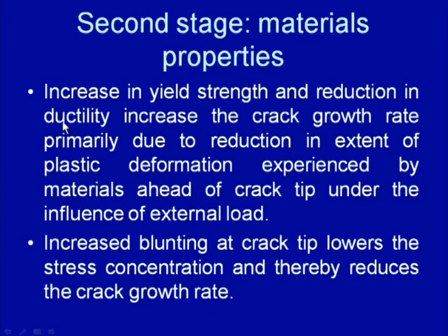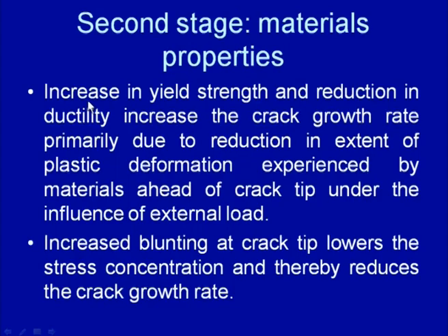Then material properties like an increase in yield strength and a reduction in ductility increase the crack growth rate, due to the reduction in the extent of plastic deformation that will be experienced by the material ahead of the crack tip under the influence of external load. Because of the limited deformation at the crack tip, stresses will be more localized and more concentrated at the tip of the crack, and that will facilitate the growth of the crack easily. That is why a material of high yield strength and low ductility offers a higher crack growth rate as compared to a low yield strength and high ductility material.